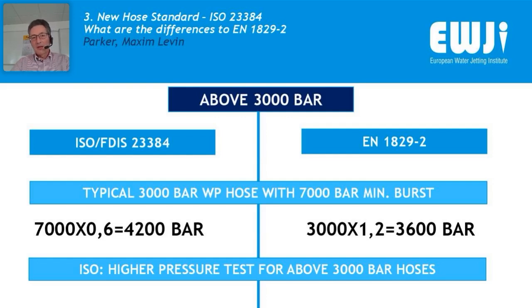Those hoses have typically 7000 bar minimum burst pressure. According to the EN standard, they shall be proof pressure tested at 3600 bar. The new ISO says it's 60% of burst, and that will be 4200 bar.